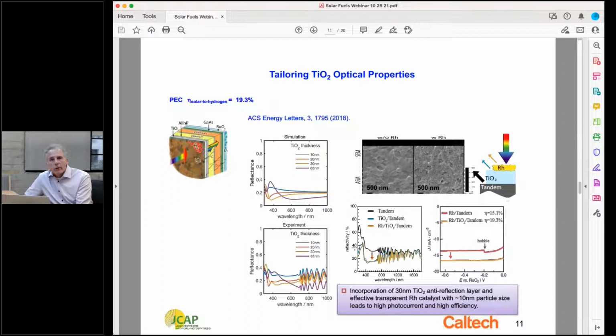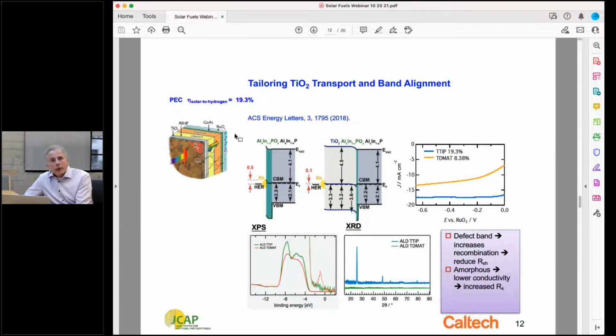If we look at the reflectivity of the tandem photoelectrode decorated with rhodium catalyst, enough catalyst to keep up with the catalytic turnover dictated by the photocurrent density under one sun, then the reflectivity is equivalent to that without a catalyst, which is a way of showing that this catalyst is effectively transparent across the visible spectrum. This catalyst is supported on a titanium dioxide protective coating, and its thickness is tailored to be an anti-reflective coating.